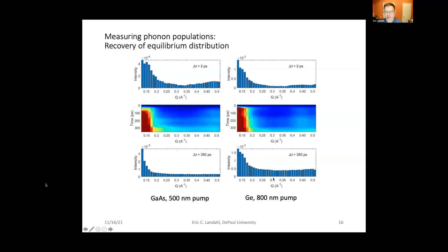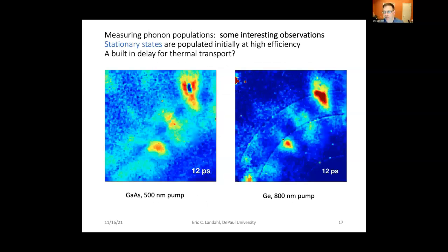Eventually, you always get back to thermal distribution, of course. In that case, it takes about 350 picoseconds, and the gallium arsenide in particular is not cool, but now at a definable temperature. In this case, I think it is about 20 degrees above room temperature. Just a couple observations on this new data set.